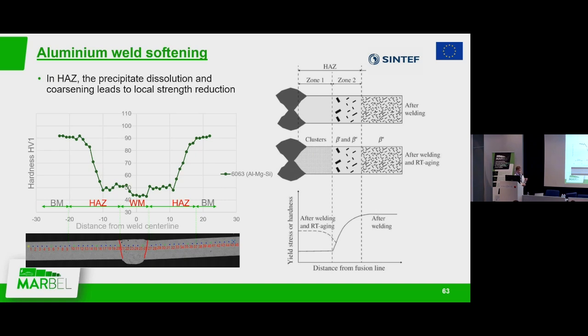What we see here are hardness values, and the hardness values in the weld metal are really low, and this is approximately the same as the yield strength. So the yield strength outside is close to 100. In the weld metal, it is less than 50. Outside in the heat affected zone, it is also around 50 and upwards. So you have actually lost all the performance of the weld. And this is due to this effect.